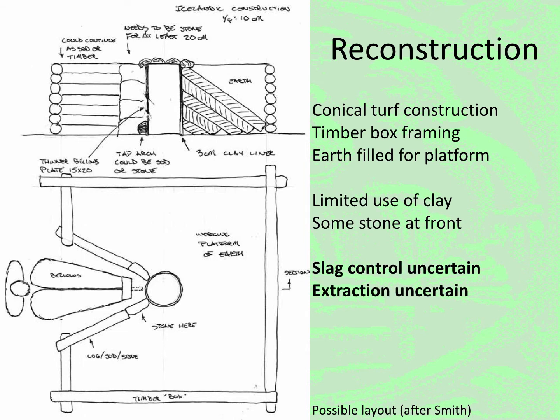The relatively small amount of tap slag recovered, as well as the heavy slag blocks found, suggest that furnaces may have been constructed with space to allow slag to accumulate. Without either stone or clay to support the front wall of the furnace, extraction may have actually been undertaken from the flat platform at the top of each furnace.